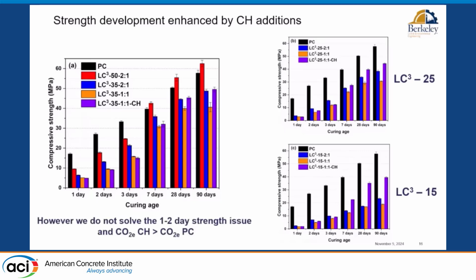But of course, and this is what I was trying to say at the beginning, please don't take home that this is a good idea from an environmental point of view, because actually, if we decarbonate limestone to produce calcium hydroxide, the CO2 footprint is actually higher than Portland cement, so it would be better to keep the clinker factor higher. But from a chemical point of view, I think that is a nice perspective, because if we find a way to produce calcium hydroxide or hydraulic lime in a cleaner way, or if we manage to design a process where we can fully capture that CO2 and utilize it somewhere else, well, then maybe one day this could make sense, but certainly not decarbonating calcite to do it.